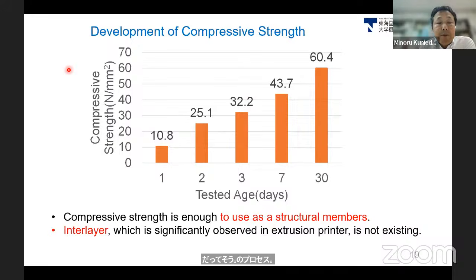Through that technique, the compressive strength is very easy to gain. So this is the relationship between the compressive strength and tested age. And after 1 month, 60 megapascal is obtained. So the compressive strength is enough to use for structural members. And the interlayer, which is significantly observed in the extrusion printer, does not exist. I mean that more homogeneous material has been obtained.